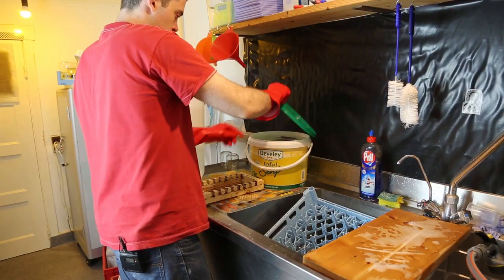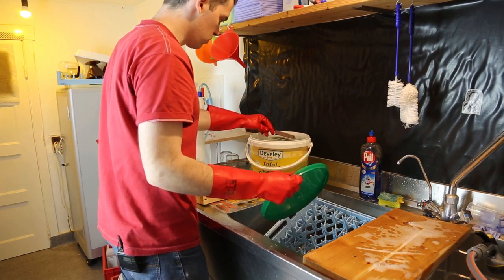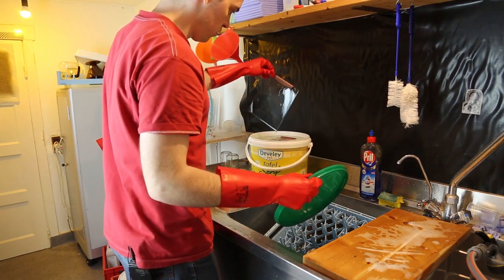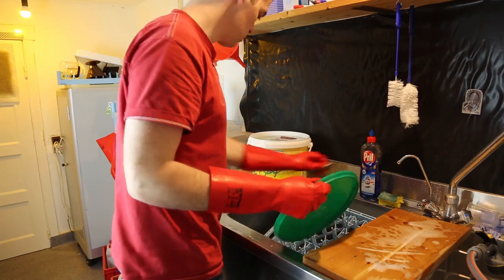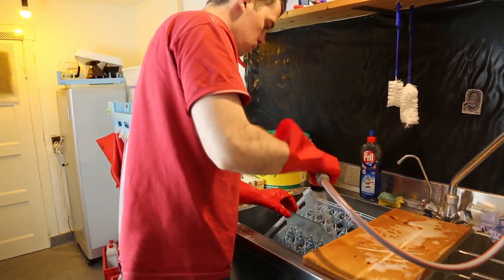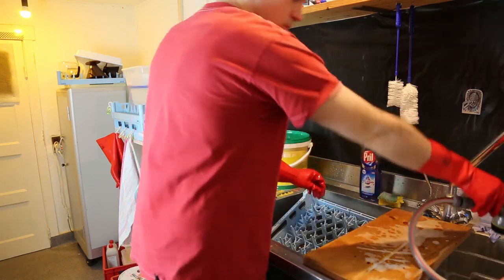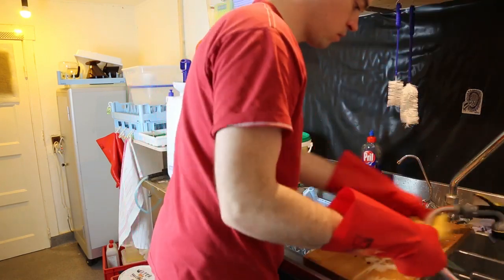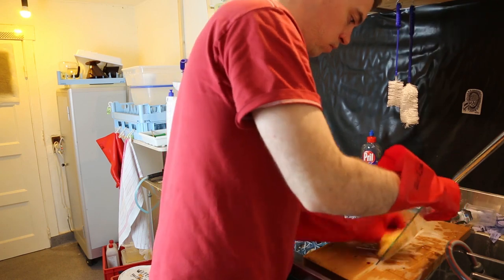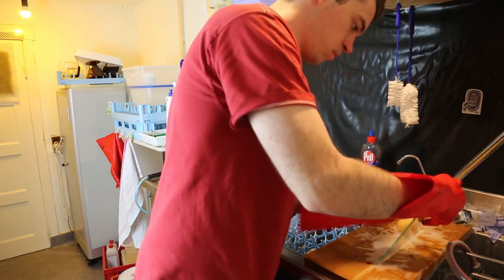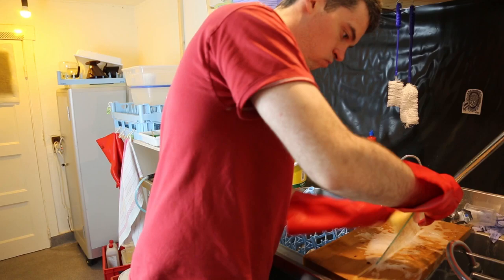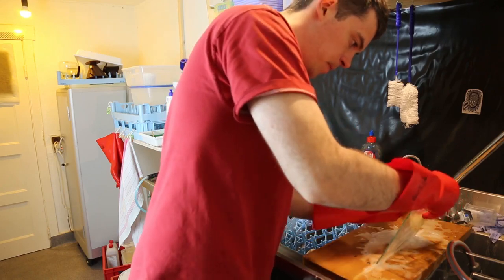After 12 hours, I take the plate out of the acid tank and scrub it with a very soft sponge and dishwashing soap. I scrub it from left to right and in an up and down motion. When scrubbing, you will notice that one side of the glass feels a little rougher than the other side. One side will provide more friction when scrubbing it and also make more of a squeaking sound.